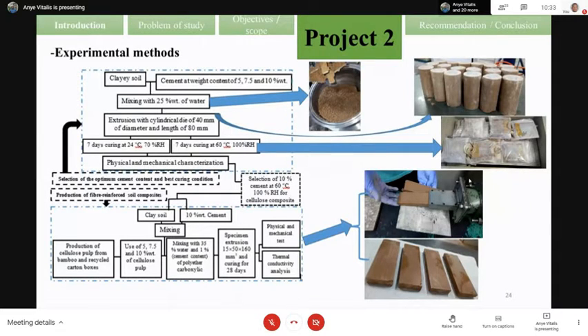We realize that by using 10% of the fiber in the material at a temperature of 60 degrees and a relative humidity of 100%, we have a significantly high mechanical property, a low water absorption and porosity. Later, the composite has been used now. We decided to use 10% of cellulose or cement as our reference material.